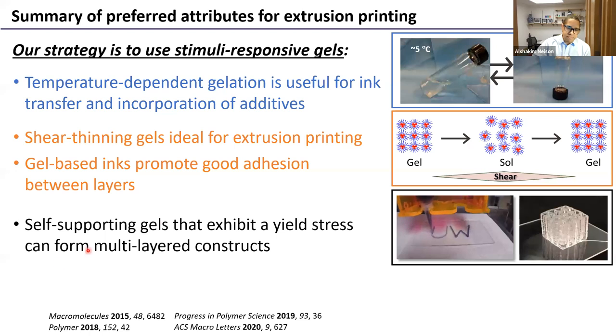So the next important feature of these gels is that they shear thin. And so what we do is we transfer these gels into a syringe. We fit a nozzle to the end of the syringe. And then if we apply a pressure, then this gel will flow out of the nozzle. But then once it exits the nozzle, it regains its gel state again. Okay, and so this allows us to extrude this gel into very nice filaments.